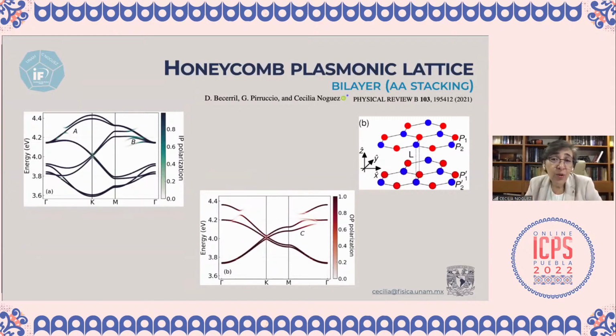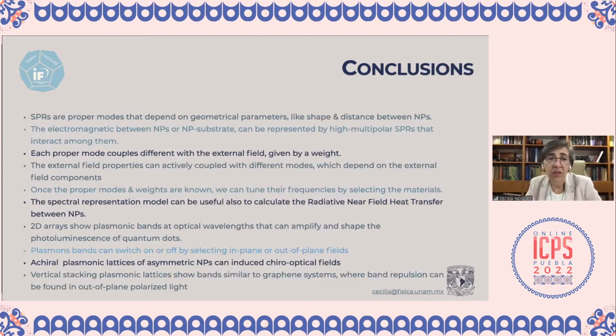And now you can also have two kinds of honeycomb plasmonic lattices. One is a stacking by layers of honeycomb plasmonic lattices. And also, like in graphene, you can have this kind of forbidden or avoided crossing of the bands here. And you can, in some way, control it by looking again at the in-plane and out-of-plane modes of the nanoparticles.